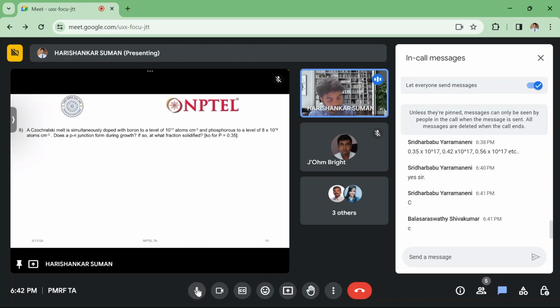So next question. The Czochralski melt is simultaneously doped with boron at a level of 10 to the power 17 atoms per centimeter cube and phosphorus at a level of 8 times 10 to the power 16 atoms per centimeter cube. Does a p-n junction form during this growth? And if so, what is the fraction solidified?